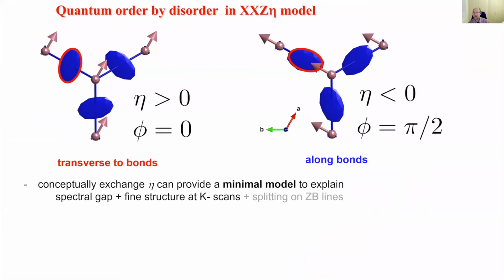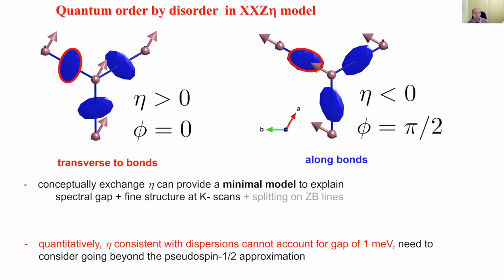Now, does that explain the actual physics in this material? So we've shown that this anisotropic interaction can provide a minimal model within the effective spin-one-half picture to explain fundamentally why there should be a ground state selection, why there should be a gap, and then also other features in the experimental data, this fine structure for K-point scans and some additional splitting on the zone boundaries. They can all be explained qualitatively. However, one difficulty with this explanation is that in order to observe the gap that we see experimentally at 1 meV, we need quite a large anisotropy that then is not compatible with the high energy changes. So then we're looking for another possible mechanism. And so for that, I want to come back to consider the other degrees of freedom in the system, the orbital degrees of freedom.